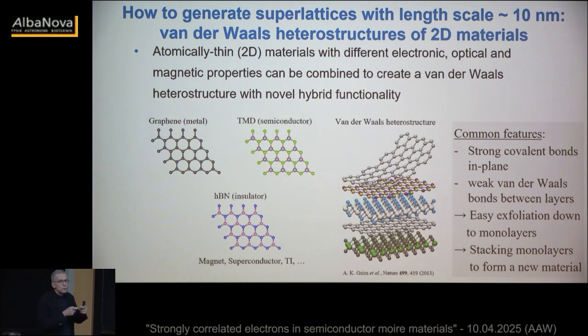So these are materials which have strong covalent bonds in the plane and weak van der Waals coupling between the layers. So they're called layered materials, and this has a very important consequence: you can actually use Scotch tape or some variant of it to peel off material down to a monolayer level. This was first done for graphene by Andre Geim and Kostya Novoselov. And the idea is that you can, with relatively high success rate, go to a monolayer of, say, graphene, which is a semi-metal.